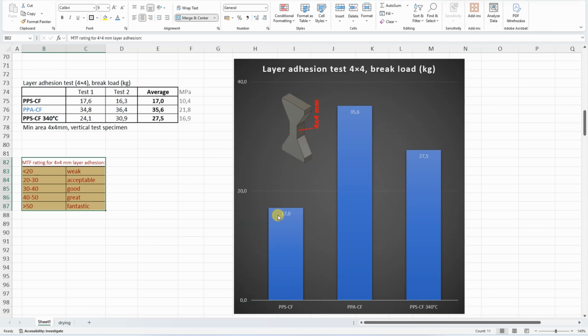But I believe that they advise this 320 degrees Celsius because of their X1E, because this is the maximum temperature for it. But look at this, printed at 340 degrees Celsius, the improvement is very noticeable, and I believe that we can go even higher, so definitely I would recommend you to try 350 degrees Celsius, and the layer adhesion will be somewhere between acceptable and good.